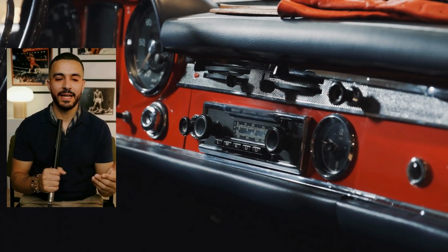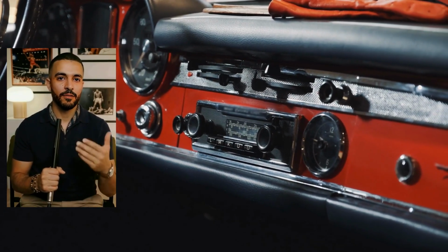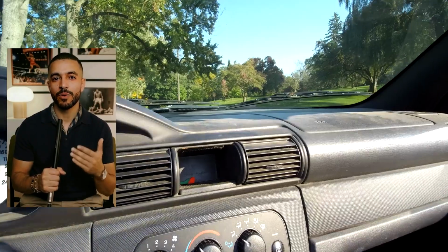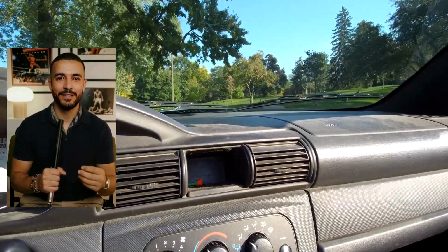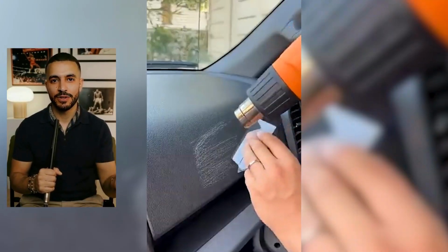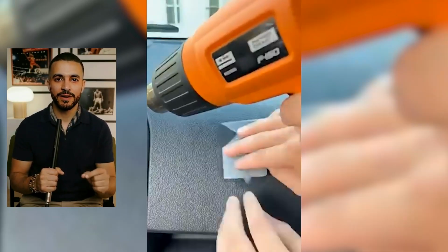Worse, you've thinned the plastic. You've made it more brittle. If you linger too long in one spot, you'll warp it or melt it. And the fumes you're inhaling? Heated plastics release things you don't want in your lungs. This method is a parlor trick. It's the automotive equivalent of putting duct tape on a leak. It looks like a fix until it fails catastrophically.